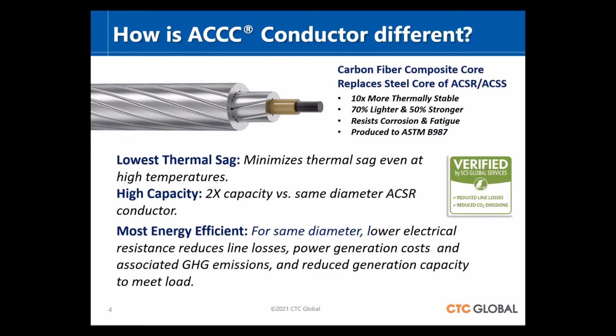And it's the most energy efficient wire. So for the same diameter, you get about 28% more aluminum on the wire. And that means that at every ampacity, every amount of amps running through the wire, the resistance is lower and the line losses are about 30% lower at every ampacity, every temperature. It's running at a lower temperature. I'll get into that in a second.